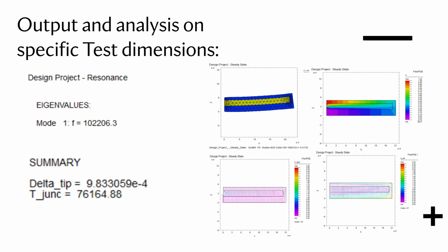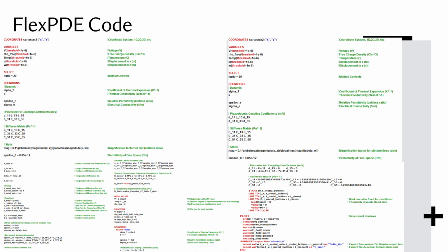The resonant frequency was found to be dependent on the shape and material of the structure and not the external stress applied, as confirmed by changing the values of the electric field and temperature difference without affecting the frequency output. Based on the above evidence, it can be concluded that the developed model is accurate to a certain degree and validated using various methods. The FlexPDE code here was constructed to validate the model, which corroborates with the results and the theoretical calculated values within a certain degree. Validation methods outlined confirm that the model is accurate and can be relied upon for further analysis.